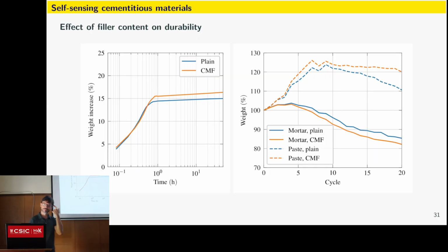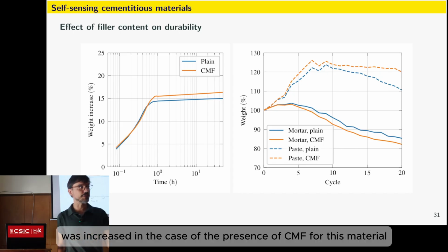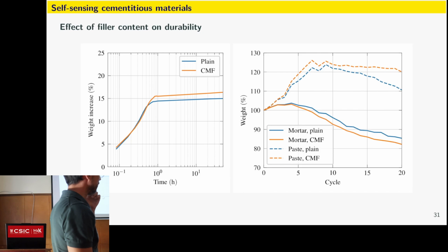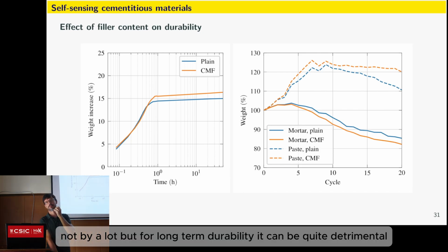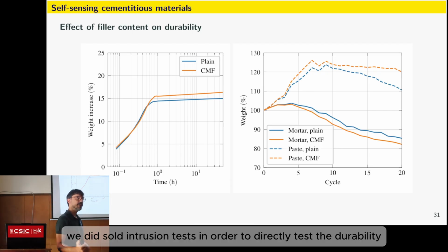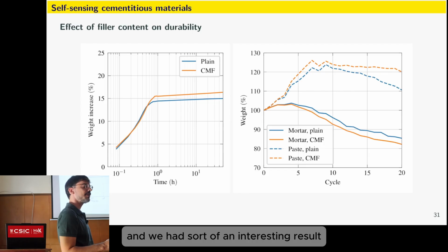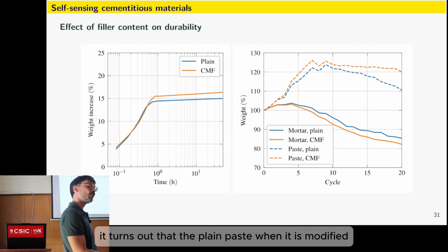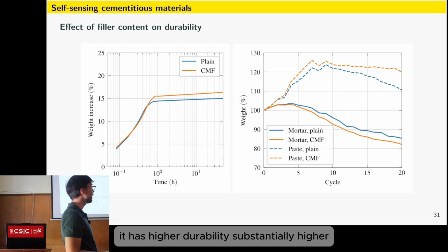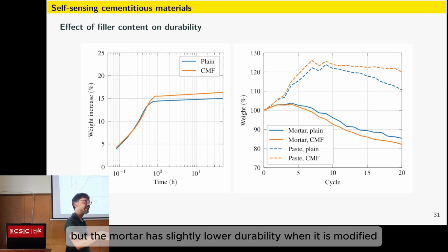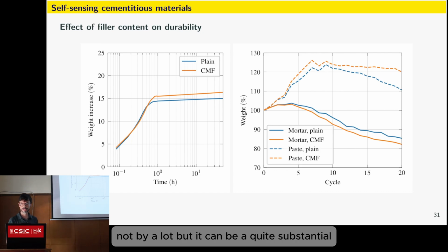Now, regarding durability, some more bad news. Water absorption was increased in the case of the presence of CMF for this material. Not by a lot, but for long-term durability, it can be quite detrimental. And we also did salt intrusion tests in order to directly test the durability, and we had an interesting result. It turns out that the plain paste, when it is modified, has substantially higher durability, but the mortar has slightly lower durability when it is modified. Not by a lot, but it can be quite substantial.